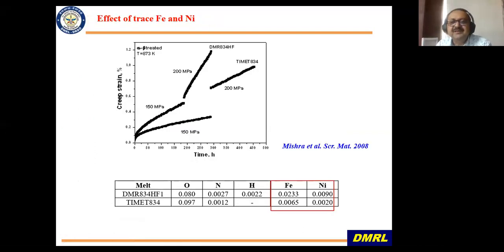Here I am showing you the effect of very, very low amounts of iron and nickel, and why they are very important. Here there are two alloys which were melted with different amounts of iron and nickel. You can see they are at the ppm level. This is 65 ppm iron. This is 233 ppm of iron, and also nickel. Both act synergistically to reduce the creep resistance. It basically causes anomalous diffusion, and that is why it spoils the creep.